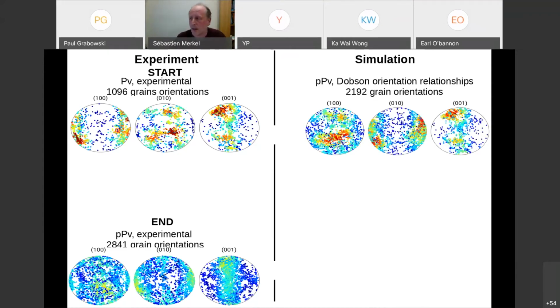So you can say for each grain of perovskite, I know this perovskite is going to have 2 daughters, and these daughters are going to be with this orientation. And so if you perform this simulation, this is a simulated pattern. So this is a simulated grain orientation, and over here is a measured grain orientation in the experiment. And there's a pretty good match. I mean, it's not perfect, but some features are the same.